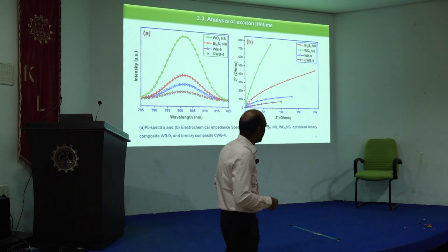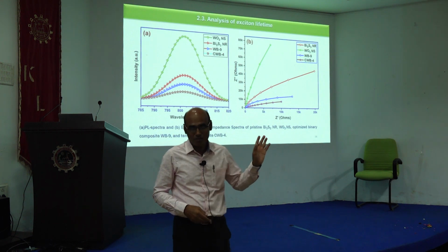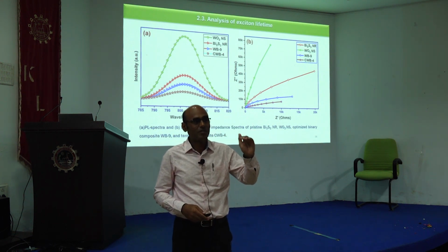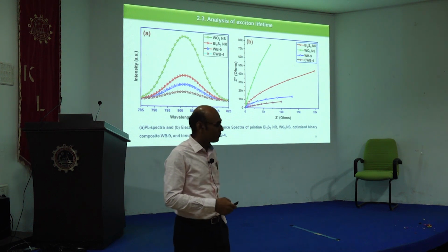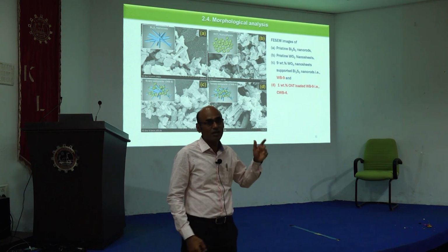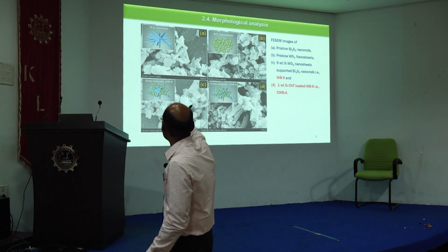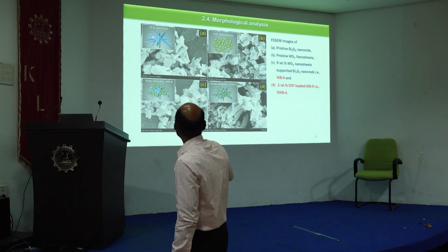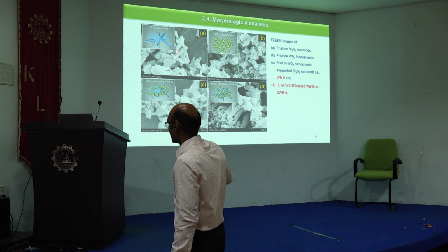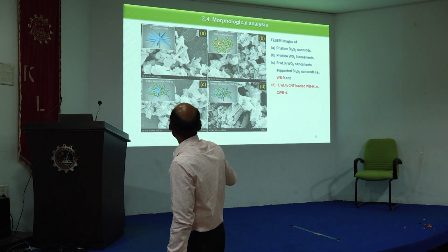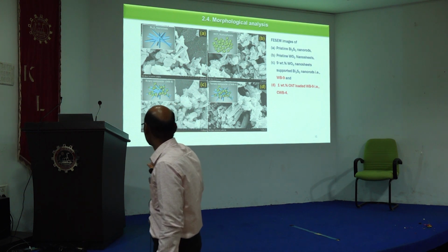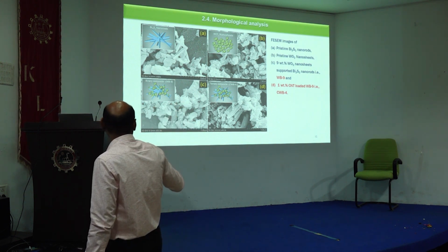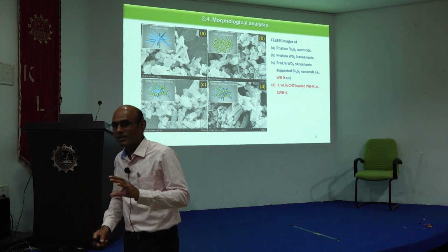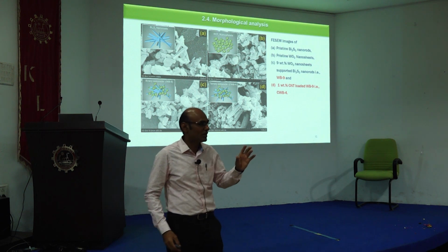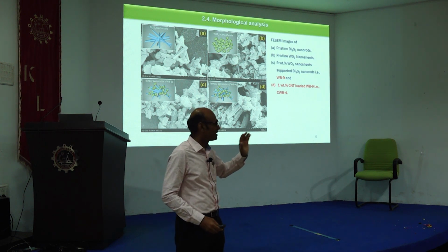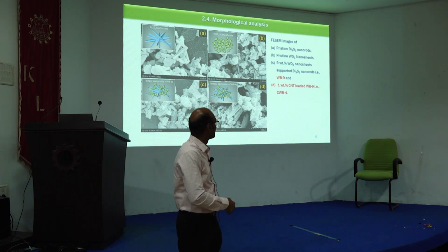Coming to the EIS, you can say that the ternary material has a better charge carrier transfer to the surface compared to the pristine materials as well. And then we confirmed the morphology of the material. You can see, for easy understanding, a nanorod shape for the bismuth sulfide, whereas the tungsten trioxide has a sheet-like morphology, and for the composites you can see a mixture, with nanotubes also in the last one, the ternary composite. The materials each carry an individual morphology. When we mix them, sometimes it is stable, sometimes unstable. Here it shows a stable morphology for the prepared material.